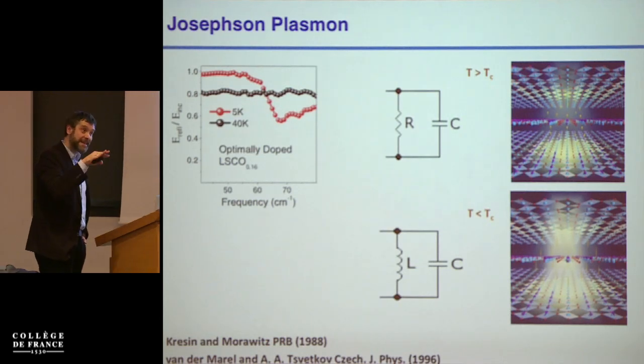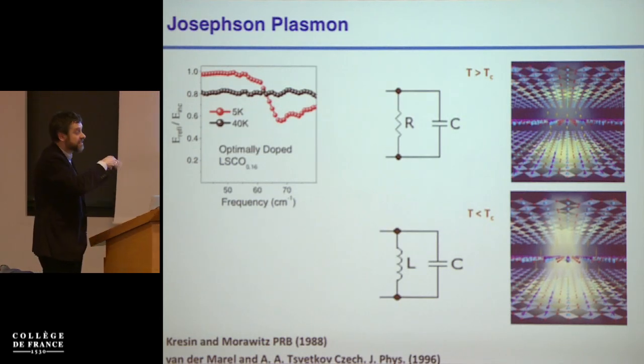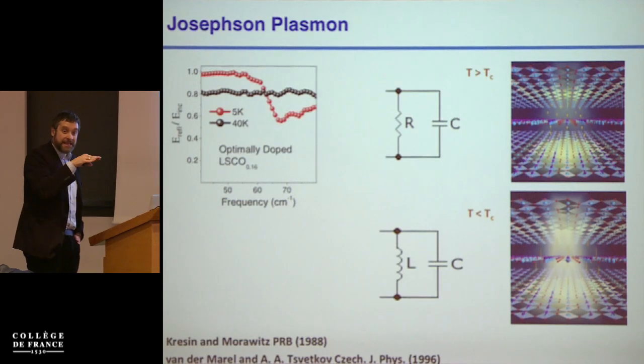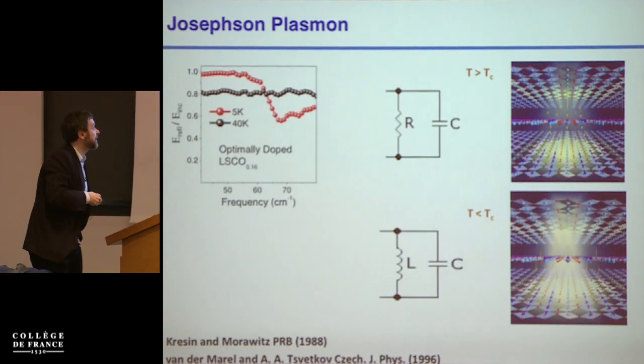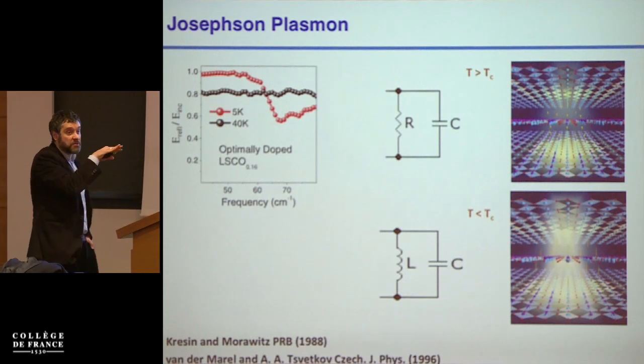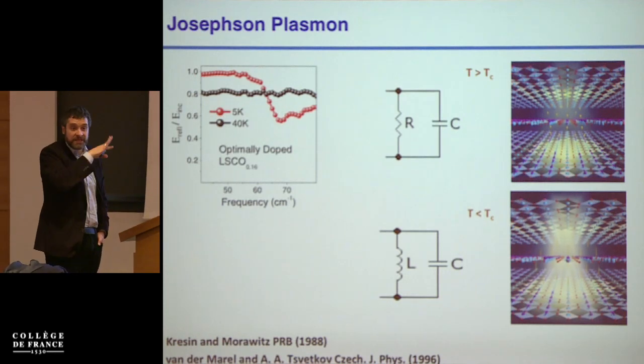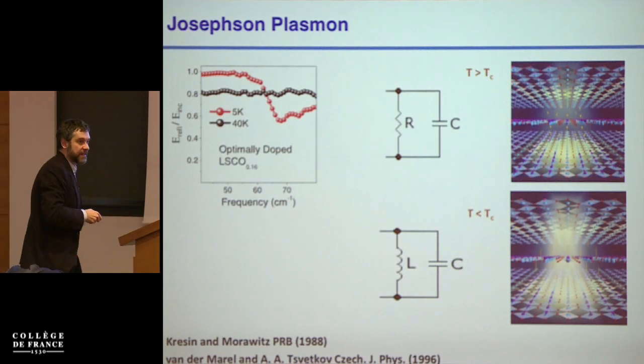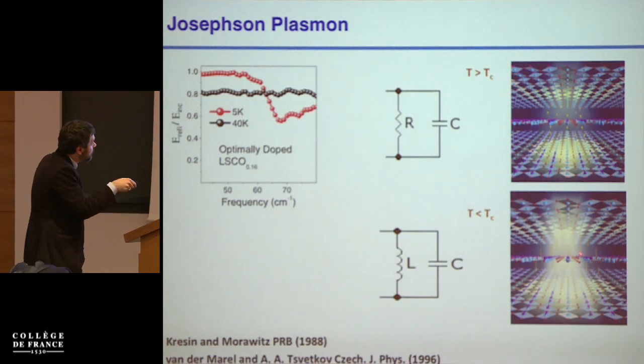So what I will find is that if this is an RC coupled system, the frequency-dependent electrodynamics will be featureless. The Fourier transform of an exponential will be something that has got no features. When I go in the superconducting state, what will happen is that the Cooper pairs will tunnel between the planes and will short this resistive transport.